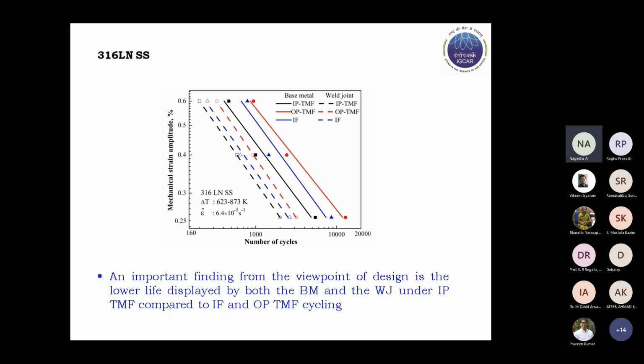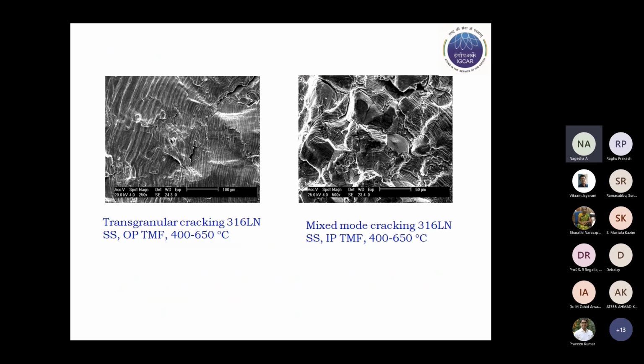So across the temperature of 623 through to 873 K, this is 350 to 600 degrees centigrade, as a function of mechanical strain, the cyclic life variation is presented here. And as we can see, for both the base metal as well as the weld joint, the life under in-phase TMF is shown to be the lowest, and the isothermal cycling at the maximum temperature gave values almost in between the values displayed by the IP and OP TMF conditions.